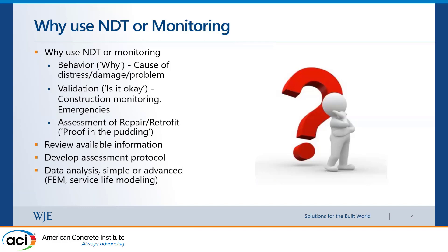The last bucket is assessment of repair or retrofit. This is something we often do when we have a new kind of repair detail and want to make sure it's actually working. We may go back after a few months and do NDT — for example, to check if epoxy injections used to fill cracks are still in place with no debonding. For floor strengthening to fix a flexible floor issue, you measure vibrations because we rely on models to come up with fixes, and you need to verify your model predictions were accurate.